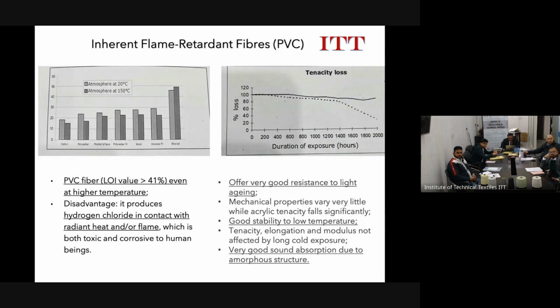And you can see that LOI is very high. And here also you can see that LOI is high even at the higher temperature. So you can do LOI testing at room temperature, but then it's performing with better LOI at higher temperature. So all testing is done at room temperature, but then also at higher temperature to check the extreme condition. So you can see the trend, which we also need to follow.